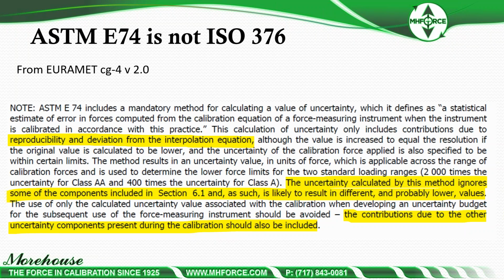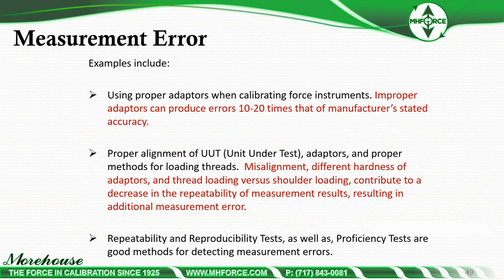Recommendation, it's basically saying that ASTM is missing several things that ISO does have as far as uncertainty. So when you get a cal with ASTM E74, by rights, you have a little more work to do to quantify all the additional error sources. And then ISO addresses adapters, and using proper adapters when calibrating force instruments. Improper adapters can produce errors 10 to 20 times that of manufacturer stated accuracy.